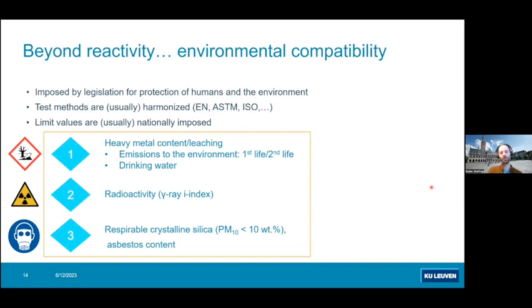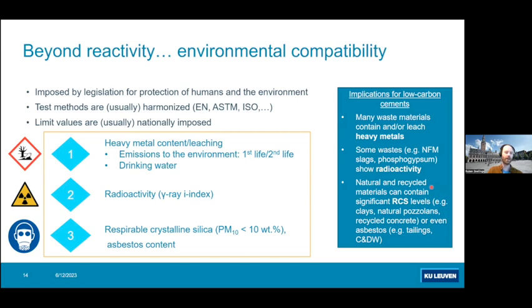The typical parameters you might want to look at are heavy metal contents, and in particular whether these heavy metals are mobile. Emissions can happen during the first life when the concrete is in place, or during the second life when it's crushed and used again as, for instance, a road-base material. Radioactivity is another one. Some of these SCMs, for instance these non-ferrous metallurgy slags, but also phosphogypsum, may contain traces of radioactive elements, so they should be tested also in terms of gamma ray radioactivity.